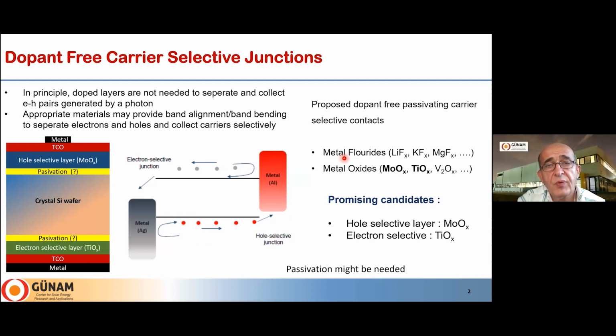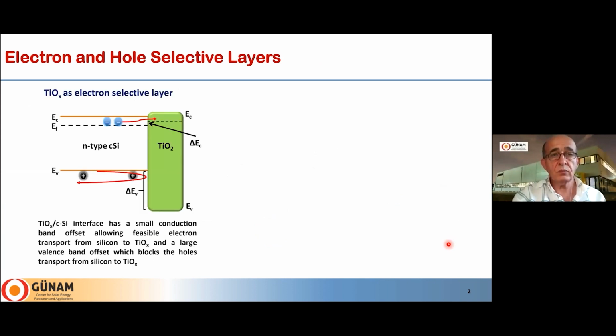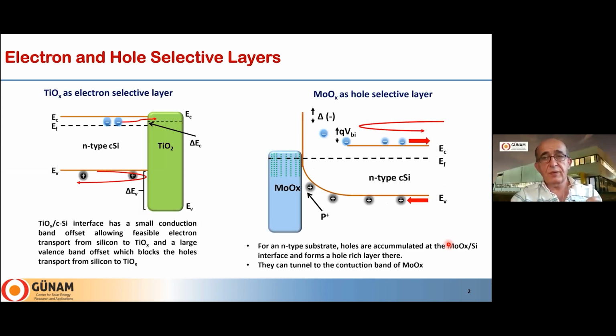So here for the electron side, I mean this side, electron selective junction, we have materials like lithium fluoride, potassium fluoride, magnesium fluoride. For the other side, we have metal oxides like molybdenum oxide, titanium oxide, and vanadium oxide. So these are the candidates, but among them, the most promising ones have been identified as molybdenum oxide and titanium oxide. So I will be focusing on these two materials in the coming slides. So let's look at these materials a little bit in detail.